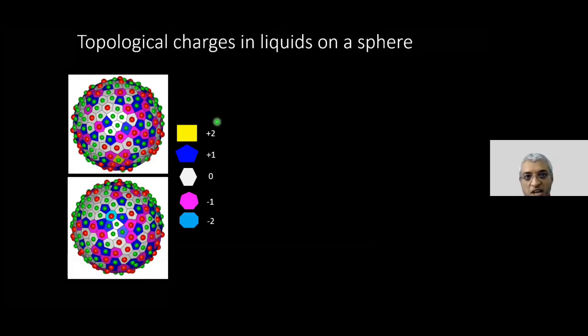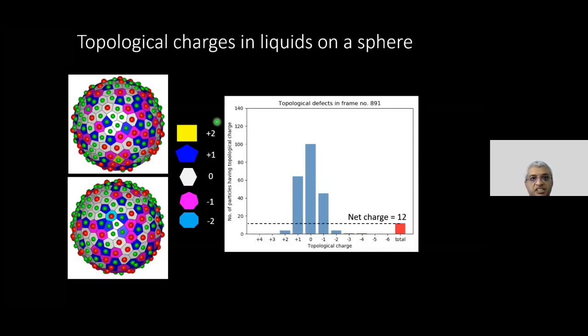We can look at the topological charges on the surface, and we see that just like for a crystal, you need 12 pentagonal defects, although the defects themselves can fluctuate. Each of these polygons that I have here I'm calling a defect. Hexagon is 0 charge, pentagon is +1 charge, heptagon is -1 charge, and so on. But they all add up to 12, which is mandated by geometry. But then these defects do fluctuate.